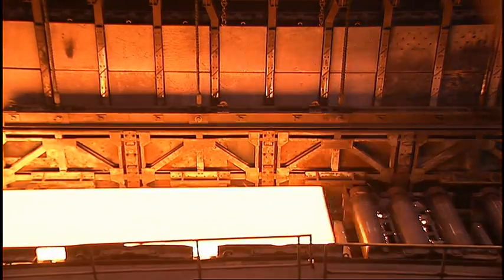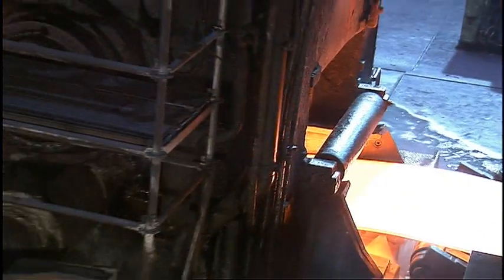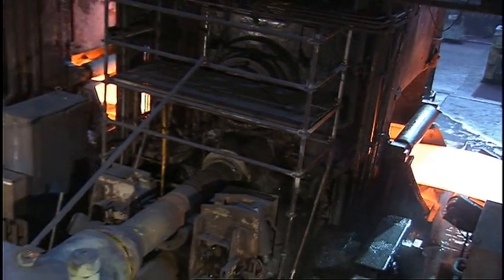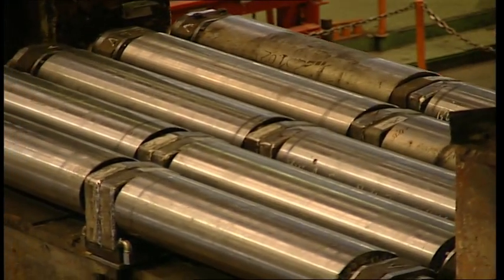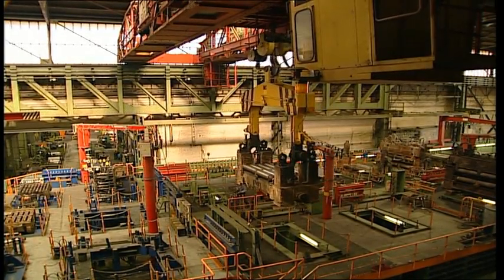Extremely low wear, a homogeneous hardness shape over the entire serviceable layer of 11 mm, and an excellent surface condition with minimal fire cracks. Without being remachined, the rolls were immediately reinstalled.